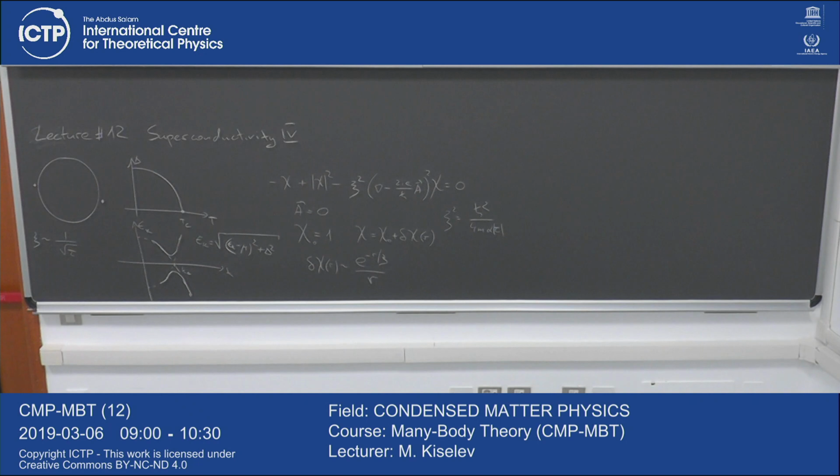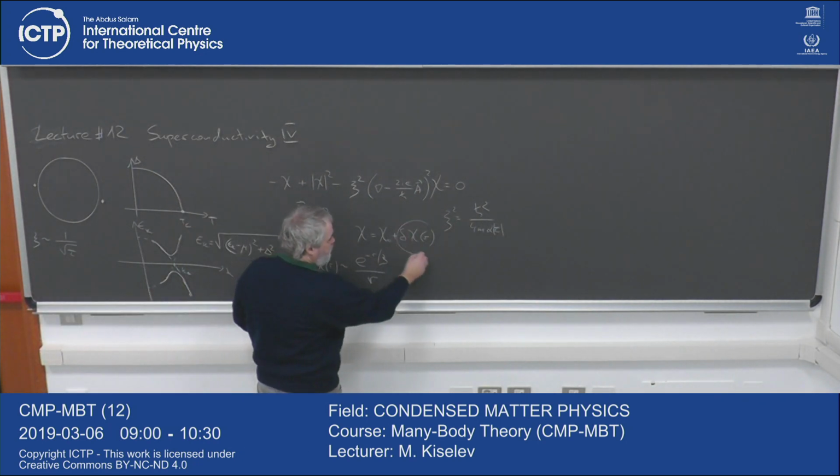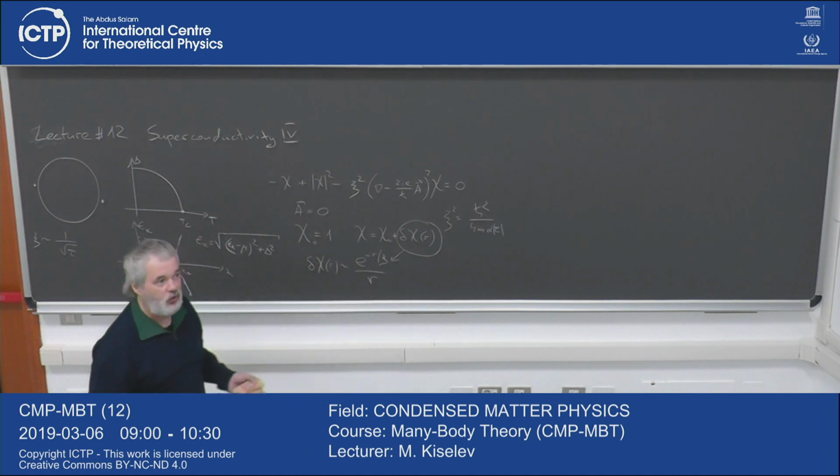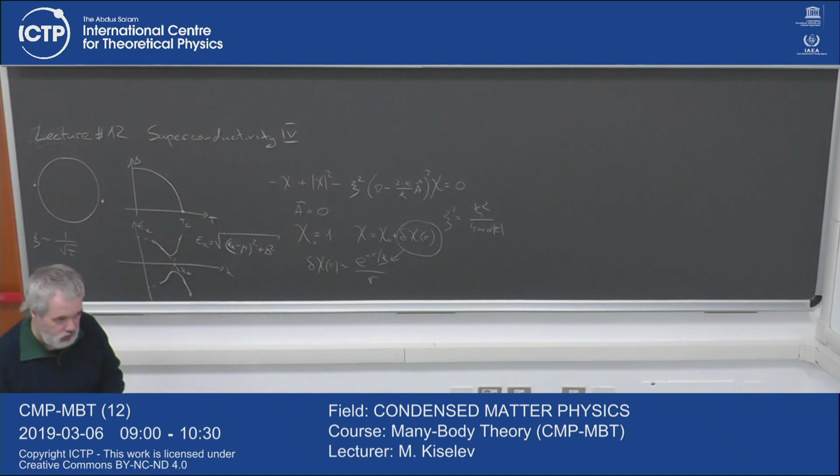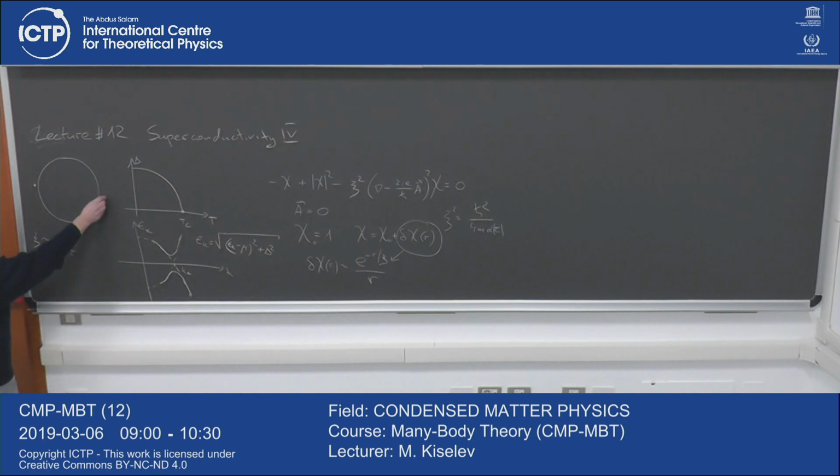And this coherence length actually defines the typical size of your wave function, and we know that the order parameter is a gap, and at the same time it's attributed to the wave function. So xi, I would say, is a typical size of the Cooper pair. And of course, since this xi is a very large quantity, we can immediately say that different Cooper pairs overlap strongly, the Cooper pair being a singlet, and we cannot discuss the Cooper pair as a bosonic quasi-particle, because the typical size of this Cooper pair is much larger compared to the mean distance between Cooper pairs.